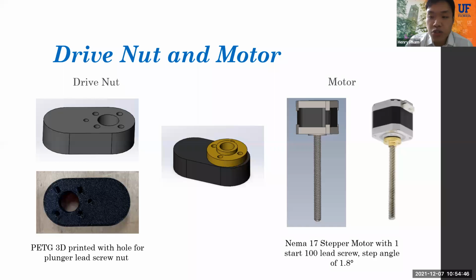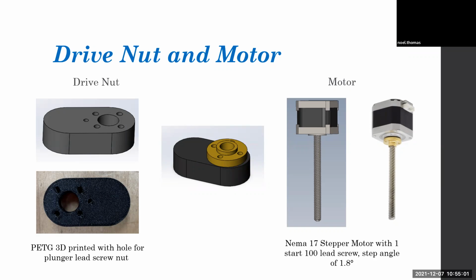So to produce linear motion in our design, we used a stepper motor with a lead screw attached to the cylindrical 3D printed part that we called the drive nut. The drive nut was printed using PETG plastic at 50% infill. And as previously mentioned, the printed drive nut was fit into the collar to prevent rotation, which produced a linear motion when the motor was used. The plunger for our pipette is also press fitted through a hole near the center of the drive nut.